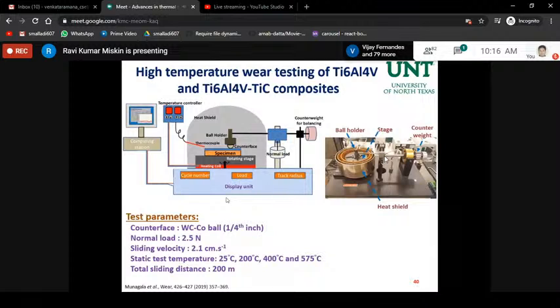So that's a line diagram. There you have a heating coil, and then you have a rotating stage on top of it, and then you keep your specimen, and there is a thermocouple. So you set your temperature using a temperature controller. So you can put in a temperature, and it heats and cools, basically. So it controls your temperature. So you wait, and there's a heat shield. So the entire setup goes into a heat shield.